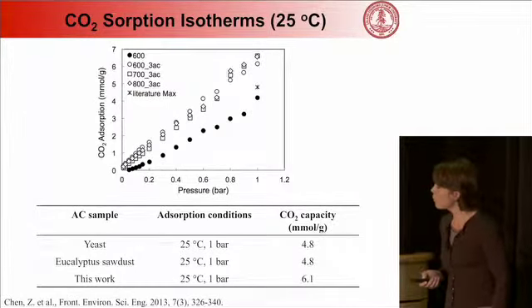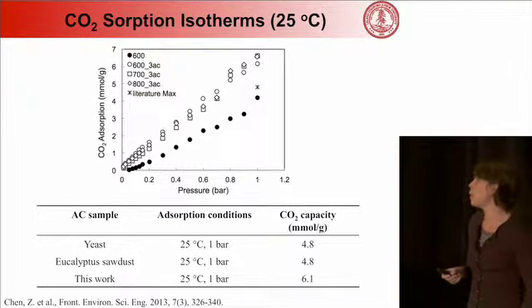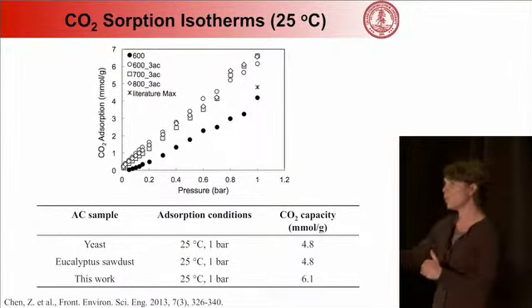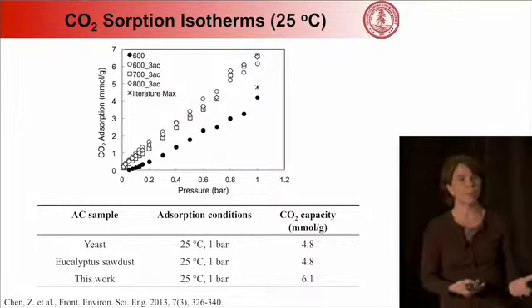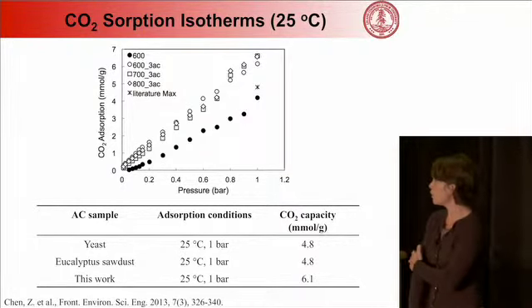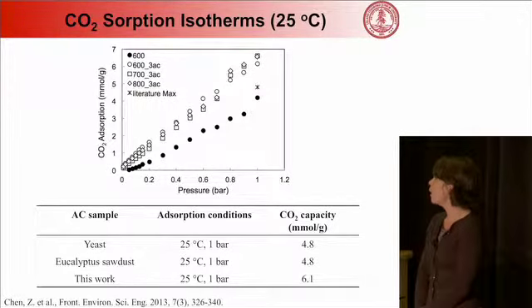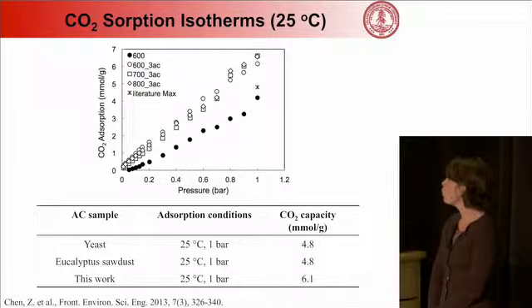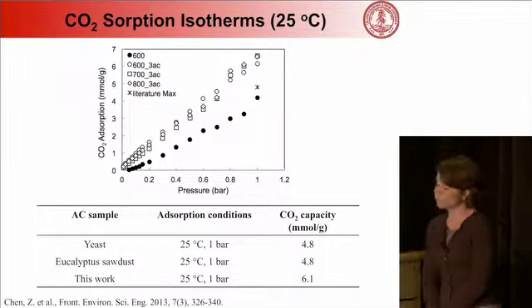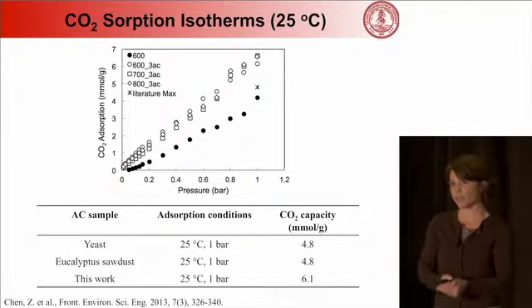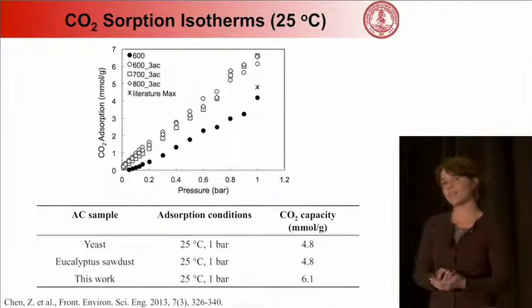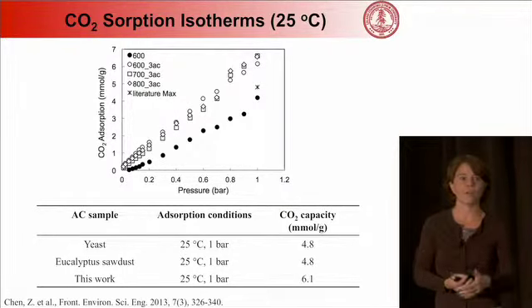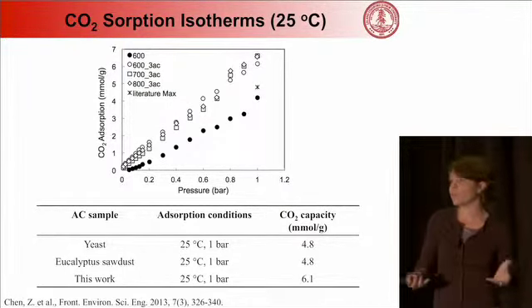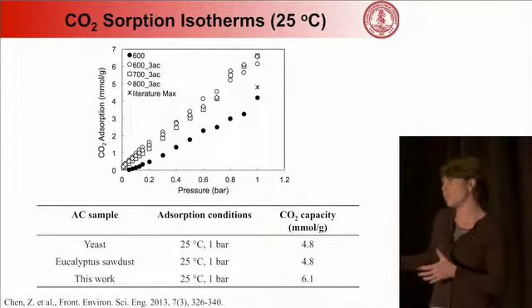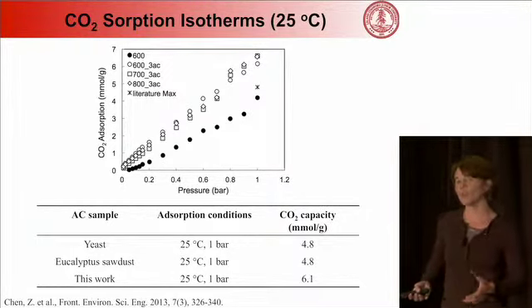So some recent work that we've done, this is looking at slightly higher concentrations. So now certainly not as high as you would see in pre-combustion or a gasification application. But in this case, the conditions are slightly higher. They're at 1 bar. But what we found is a pretty significant CO2 capacity of 6.1 millimoles per gram. And at those conditions of 1 bar, so if you look at the literature, although I said the appropriate number is 0.1, a lot of the studies in the literature actually show 1 bar. So in order for us to compare our results and to see how well our sorbent's doing, we want to actually test them at the conditions that are available in the literature as well.